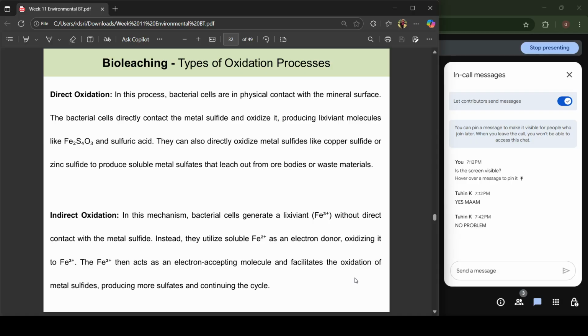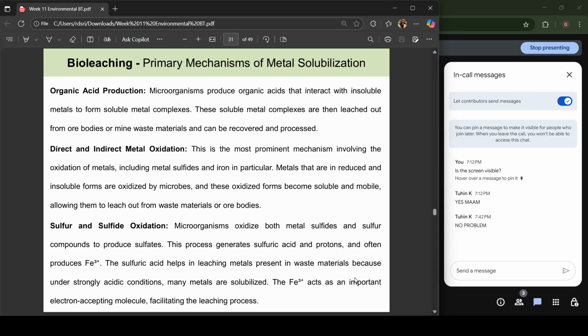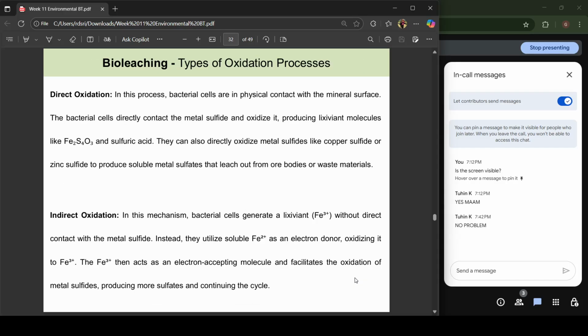So as we saw about direct and indirect metal oxidation here in the second point, we'll just see a few more details about it. In direct oxidation, the bacterial cell is in contact with the mineral surface, and it will directly oxidize the metal sulfide, producing the lixiviant molecules like Fe2(SO4)3, and sulfuric acid. It can also directly oxidize metal sulfides like copper sulfide or zinc sulfide and produce soluble metal sulfates.